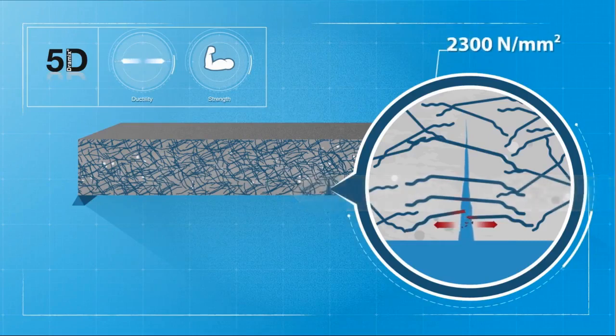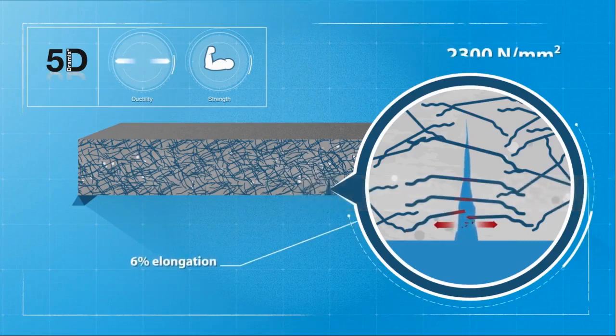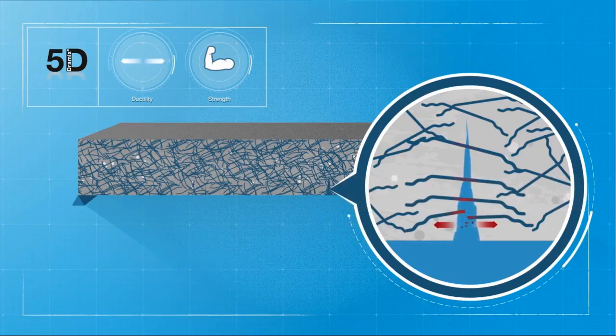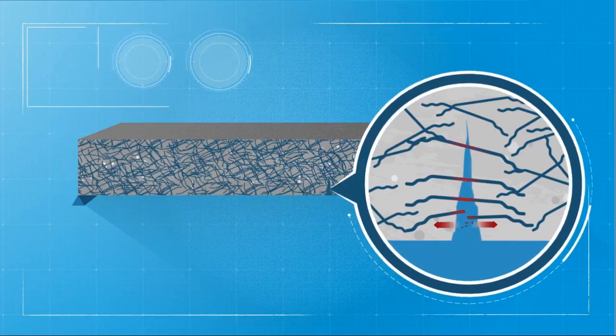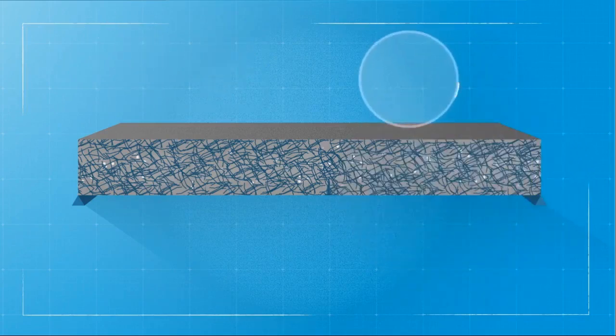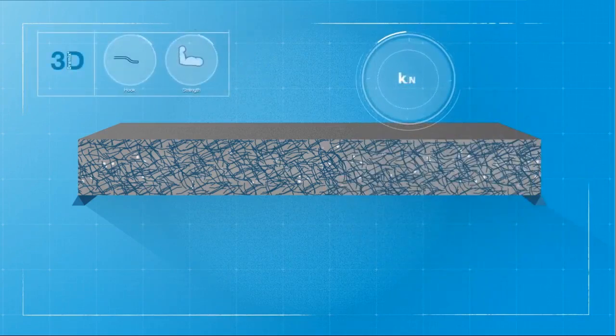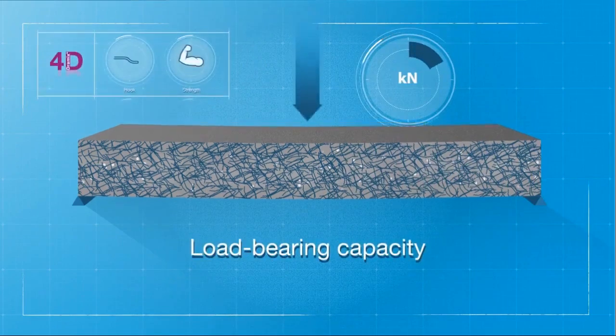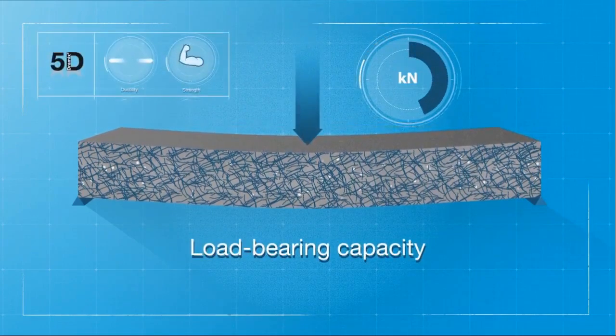With a tensile strength of 2,300 Newton per square millimeter and elongation of 6%, concrete structures reinforced with 5D can take high flexural stresses over a long period. Based on these behaviors, we can conclude that Dramix steel fibers effectively increase the load-bearing capacity of concrete.